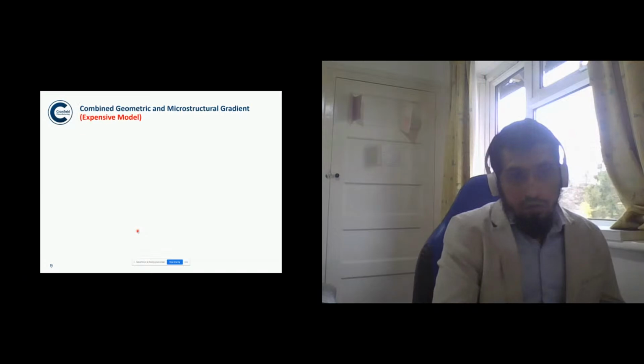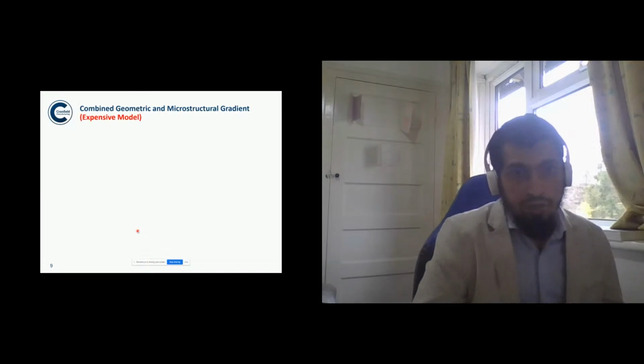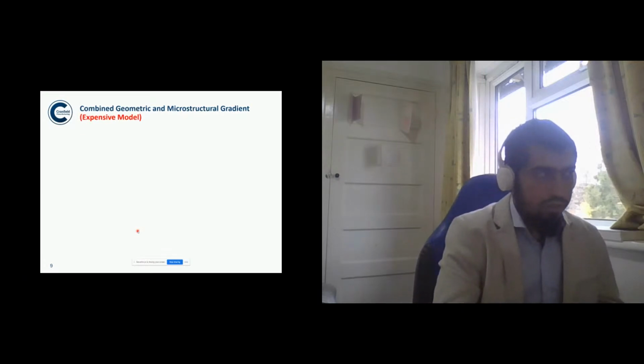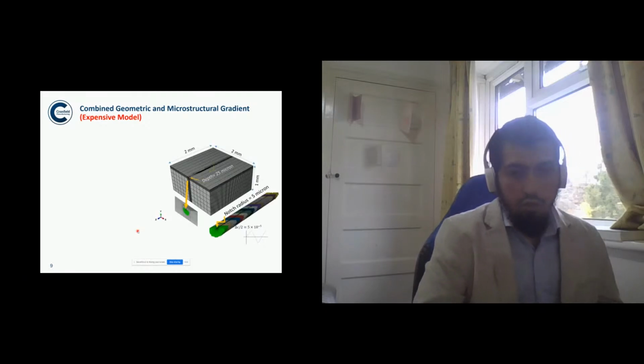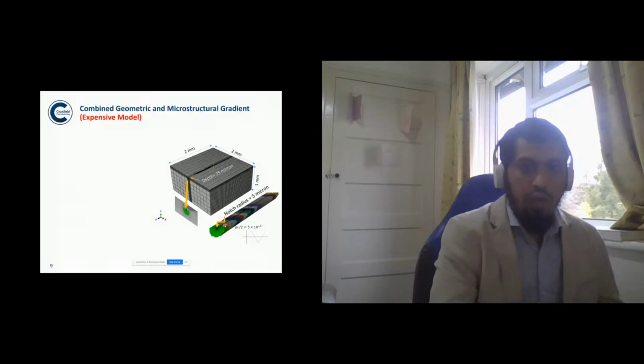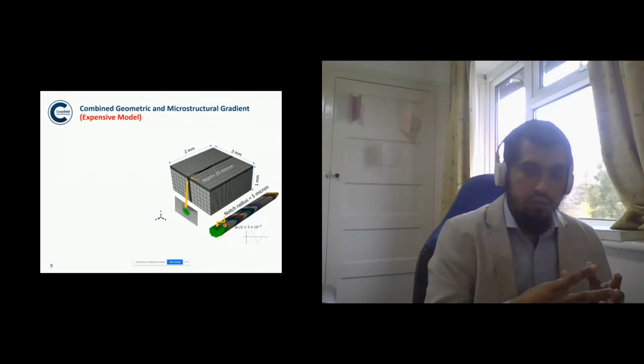Moving on, now we add in the geometric gradient with the microstructure gradient, and we termed this the expensive model. So we did a similar set of simulations as I explained in the previous slide, the same crystal plasticity simulation. Now we add in the geometric gradient with the microstructure gradient. And we adopted the same procedure as explained in the previous slide.